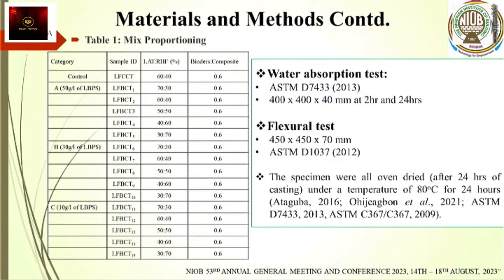Now you could see on your board the mix proportion. We have 3 categories of mixes apart from the control. The control uses cement as the binder, but we still have 60% laterite, 40% RHF. And the water to binder ratio is 0.6. So when you're talking of water binder content, it is at 0.6. Then we looked at 50 gram per liter for LBPS, while we vary, as I told you, the laterite to RHF, 70-30, 60-40, 50-50, 40-60, and 30-70. Then we also have 30 gram per liter for LBPS as binder.